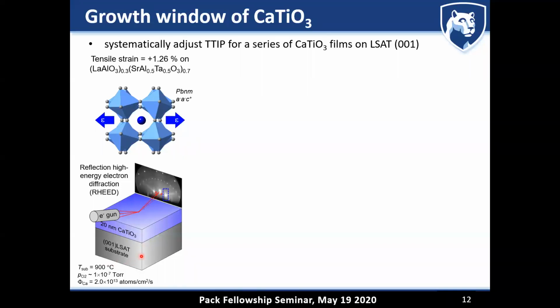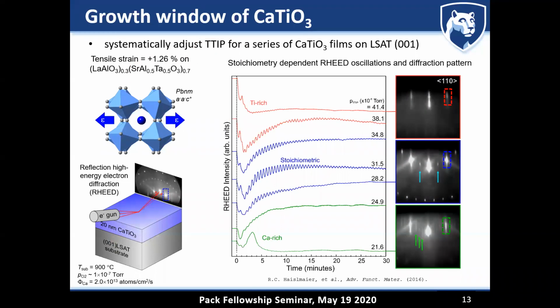And what we're going to do now is supply a fixed flux of calcium from the thermal effusion cell. In this case, we were using a flux of about 2 × 10¹³ atoms per centimeter squared per second. That gives rise to a growth rate of about 20 nanometers per hour or so. And then, in order to get the titanium into the film, because we are targeting to grow calcium titanate, we're going to adjust the flux of this titanium-containing metal organic precursor.